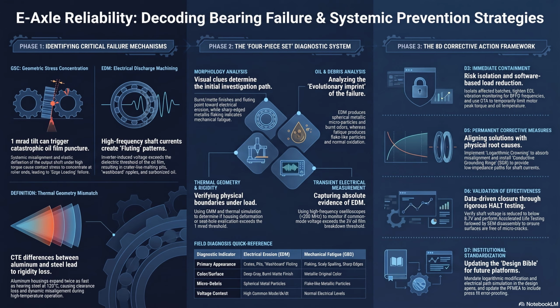They also upgrade the metallurgy to the CQI-9 heat treatment standard, dictating the precise thermal ramping and quenching process. Converting austenite to martensite uniformly for maximum fatigue resistance. And all this goes into a PFMEA, a process failure mode effects analysis. The holy grail of reliability engineering. Translating theoretical physics into factory floor reality. They put these rules on the drawings using GD&T, geometric dimensioning and tolerancing. They become critical characteristics, legally requiring suppliers to use statistical process control. If a batch deviates by a fraction of a millimeter, the line stops.